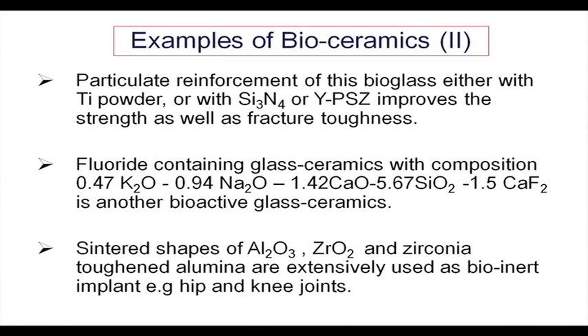As you know, both silicon nitride and partially stabilized zirconia have a fairly large fracture toughness compared to normal ceramics. So, they act as a reinforcing agent for the glass ceramics. Okay. The fluoride containing glass ceramics with compositions like 0.47 K2O, 0.94 Na2O, 1.42 CaO, 5.67 SiO2, 1.5 CaF2. This kind is another bioactive glass in addition to what we have discussed just now.